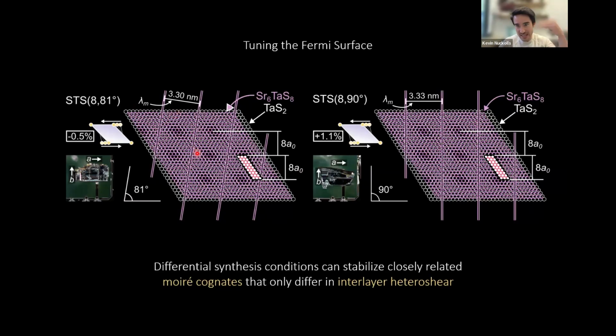So they basically have the same commensurate Brillouin zone folding, and very nearly the same Moiré superlattice wavelength, but the Moiré superlattice points along different directions. This compound, STS(8,81°), was grown at much lower temperatures and relatively quickly, and it stabilizes a Moiré superlattice that points in a low symmetry, non-crystallographic direction, whereas STS(8,90°) was grown at much, much higher temperatures and cooled super slowly in order to sweep the Moiré superlattice into this high symmetry direction. So we can perform torque magnetometry between these two types of crystal batches and compare them.